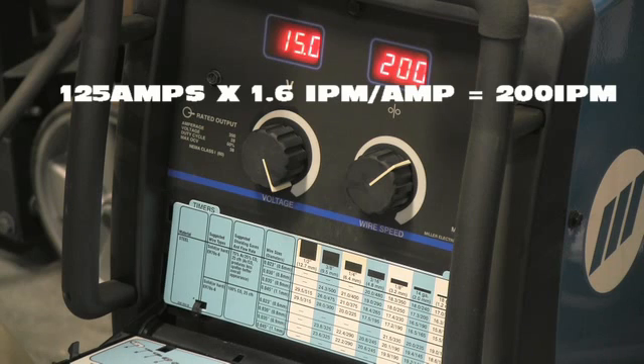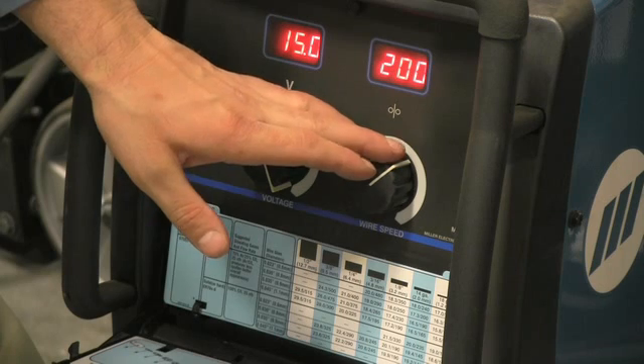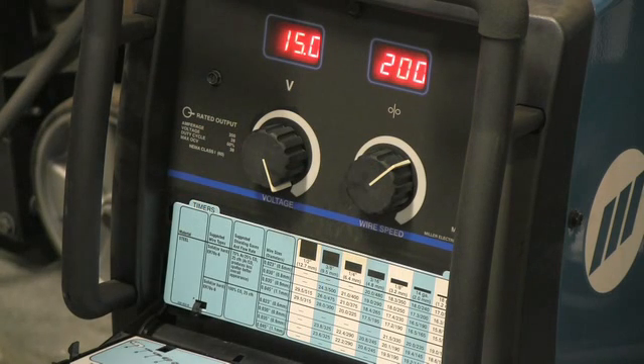So 125 times 1.6 is 200. So that's 200 inches per minute. So we'll set the machine for 200 inches per minute. Now that still leaves the voltage unclear. We don't know where to set the voltage, but we can set the voltage based off where the wire feed speed setting is at. Once we listen to the arc, we'll be able to tell which direction to go. So we're going to do that here in just a moment so you can see what it's supposed to sound like.